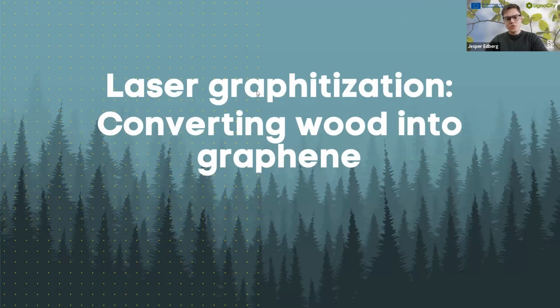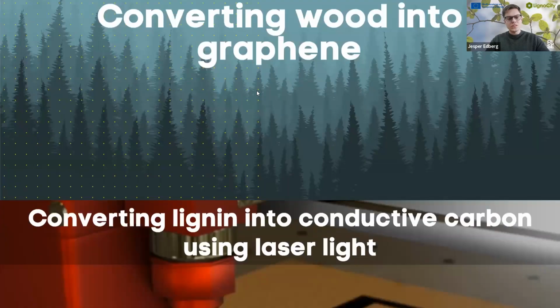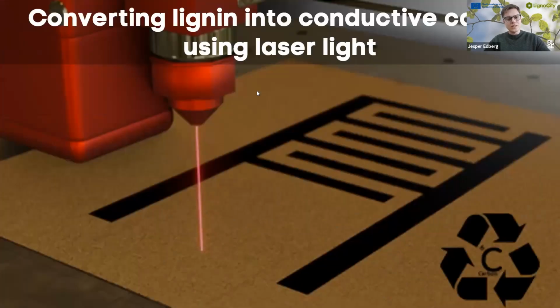So Hjalmar showed two ways of doing this. You can use basically high temperatures, like in an oven, and you can also use an electrochemical method. But one more way to do it is to use a laser. So it's basically the same principle. You heat up the lignin to very high temperatures, but you do it much more locally. And you can actually write patterns into lignin and other bio-based sources and convert it into graphite or even graphene.